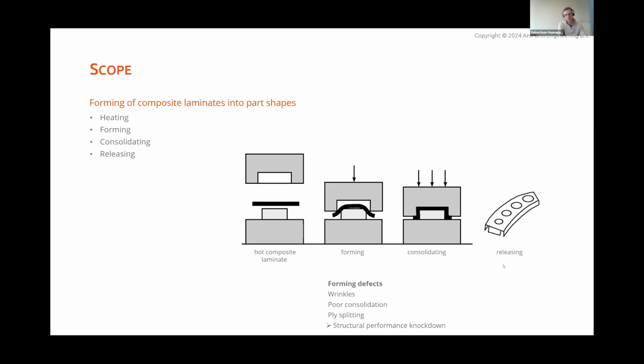During the forming, there can be some defect development, like wrinkles, some poor consolidation spots, ply splitting, well, all kinds of defects that can knock down your structural performance of the part in the end. Also, in the release stage, there's usually some geometric deviation occurring, also known as warpage or spring back, which gives some problems when doing part assembly in larger structures. It gives us fitting issues. We work on that kind of simulations as well. It's in development. That's not part of the talk today. Today's focus is on forming defects.